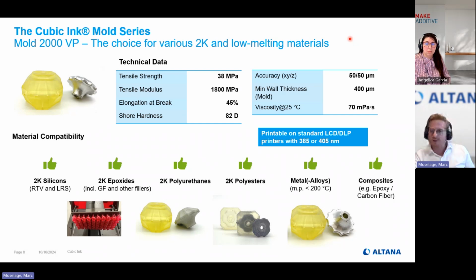So the elongation at break with 45% is pretty high, and this has a reason. If you are too rigid, so you need to be rigid, sure, but if you are too rigid, you have the risk of cracking the material. So really slight deformation may lead to cracking, and then the whole final part is ruined. So certain flexibility is necessary.